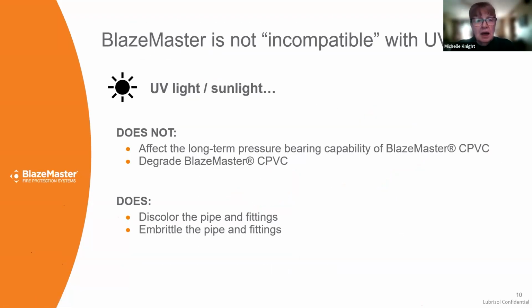So I've mentioned it already, but BlazeMaster is not incompatible with UV light. It does not affect the long-term pressure bearing capability. It does not decrease the service life of the CPVC. It may discolor it a little. The orange pigment doesn't hold up as well as the CPVC does. And it may age a little and become hard to cut.